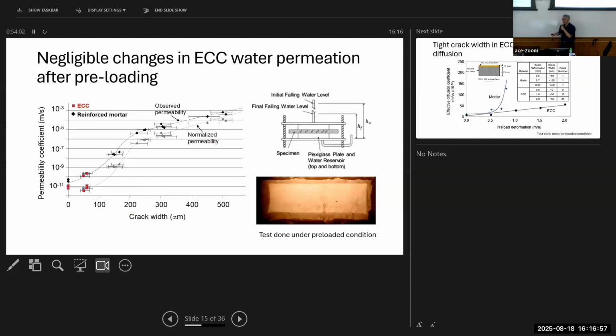Okay, so there is data that supports what I just described to you, and this is done by our group. We make a piece of the specimen. Remember I said that durability tests, even if you do them in the lab, should simulate field conditions. So we actually simulate field conditions by preloading the specimen in tension, so it creates micro cracks after the preloading condition, and then place the specimen under a hydraulic pressure.